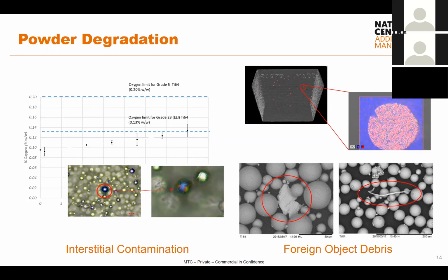So again, it's a supply chain issue. Do I know which suppliers can provide me with clean powder in the first instance? But even if it didn't have it at the start, every time I use the powder, there's a chance that I could be adding foreign object debris in there. So the two images below represent recycled powders, and they represent foreign object debris that we've found within those powders. So both of these just so happen to have chemistry that is consistent with stainless steel. Of course, it's been measured using SEM, so we can't guarantee that it's stainless steel, but the elements that are there lead us to believe it's stainless steel. And so that is likely debris from the equipment we've used to process the powder. This elongated one could very well be a part of a sieve. This could be a piece of debris from the.